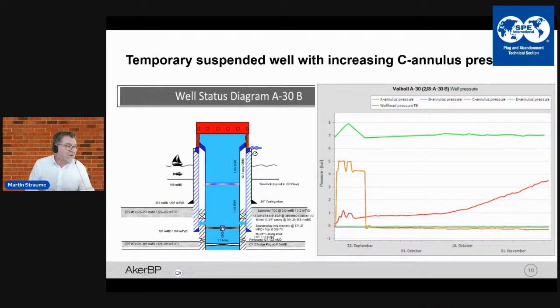But when we drilled through and removed the bismuth plug, we started to see gas coming out again, and we can see the gas pressure increasing, while the pressure inside was actually more or less zero after it had been bled down. But the C annulus pressure, the red curve, is this annulus here that is empty on this drawing. That's where it started to leak. So that was proof for us that yes, indeed, the bismuth was working, but when we removed it, it stopped working.